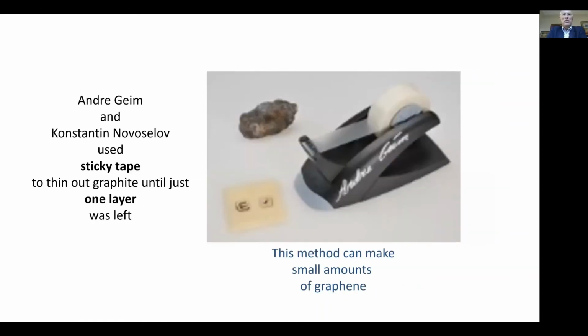Now, what Andre and Kostya did was really quite simple and yet also very clever. In order to get one single layer of atoms from graphite, they simply used sticky tape to repeatedly thin it out until just one layer was left. A very simple process, but actually it needed a lot of clever equipment to show that that is what you had got.